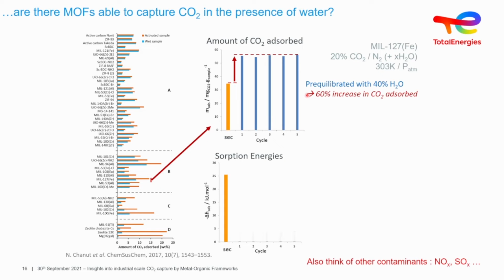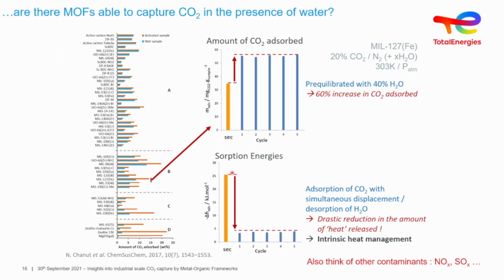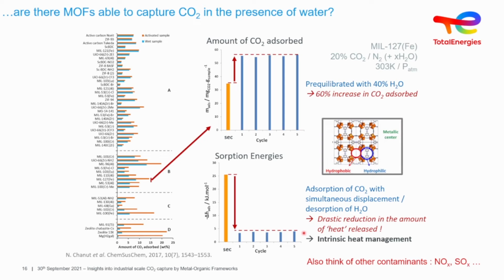What we can then do is look at the energies. We can see here that the energies decrease over various cycles. What we think is that the CO2 after the first cycle is able to push out some of the water. There's still some water available, and as we do the adsorption and the desorption, water reabsorbs during the desorption, but the CO2 pushes. And this balance between the heat of adsorption and the heat of desorption gives us these low enthalpies, these low energies here. And we can think of this as, we talk about intrinsic, so internal heat management, but it's very much a play between water and CO2. And this is, I think, a way forward. Of course, we have to think about other contaminants such as NOx and SOx.